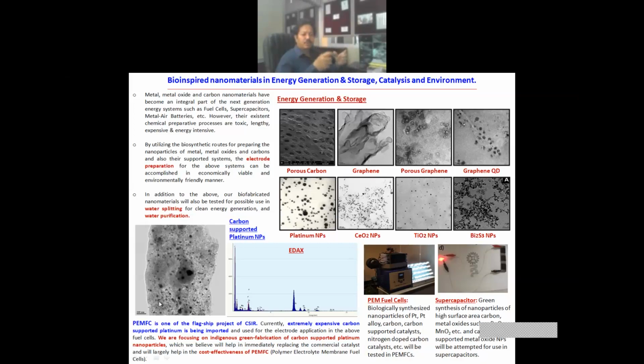Suppose you want to make the gold nanoparticle: take gold solution, add this enzyme, add this capping protein, and you will get 5 nanometer. If you do not add this capping protein, you will get 100 nanometer. This paper we have published in RSC Advances. So now we know the mechanism how the fungus converts the cadmium sulfate into cadmium sulfide nanoparticle.